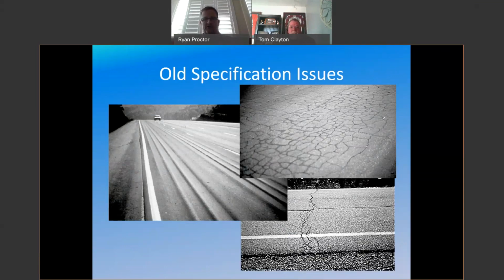So we saw a lot of roads that look like this. And one other thing I should mention, obviously the asphalt binder isn't the only cause or potential cause of some of these issues, but at the time we felt like new specifications would help improve the binder and would help improve their performance, which would help reduce these problems. So rutting was a big issue, cracking and alligator cracking, and I'll talk about those with the newer tests here in a minute.